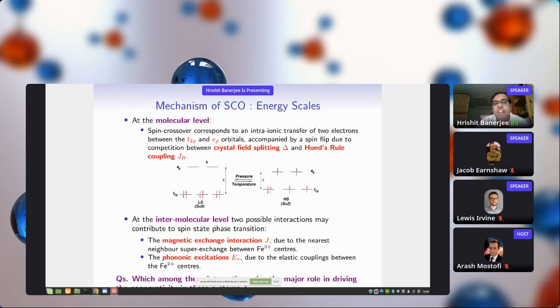When you have a large crystal field splitting, I take the example of iron 2+, which is in a d6 state. When you have a very large crystal field splitting you have all the spins paired up and you have an S equal to 0 state in the t2g, because it's an octahedral coordination, and your d orbitals are split between t2g and eg. However, when you have a small splitting between t2g and eg, the Hund's coupling wins this competition, and hence you have a spin S equal to 2 state.